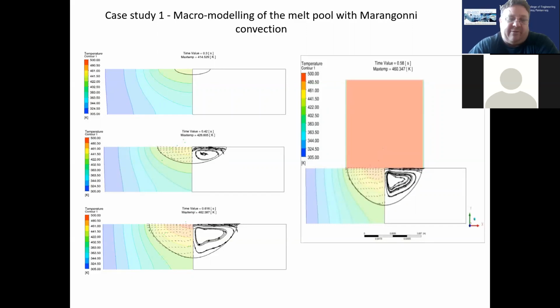Keyholing happens when you get evaporation in the center of the top, and as that evaporate forms, you get a plasma forming, and the radiation comes through the plasma and gets reflected off the sides back into the plasma, and you get an acceleration, like a boring effect. So that plasma actually bores down, and your keyhole is much deeper yet again. Okay, so what I'm talking about here is the aspect ratio. If we take the width to the depth, it will be changed by the Marangoni convection cells.